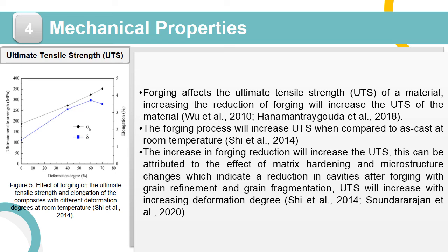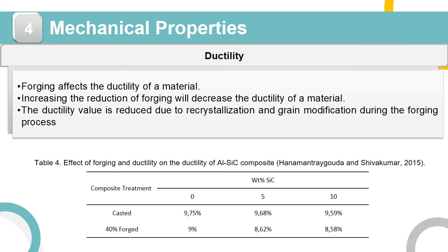This can be attributed to the effect of matrix hardening and microstructure change, which indicate a reduction in cavities after forging with grain refinement and grain fragmentation. UTS will increase with increasing deformation degree. Ductility. Forging affects the ductility of a material. Increasing the reduction of forging will decrease the ductility of a material, as we can see in table 4. The ductility value is reduced due to recrystallization and grain modification during the forging process.